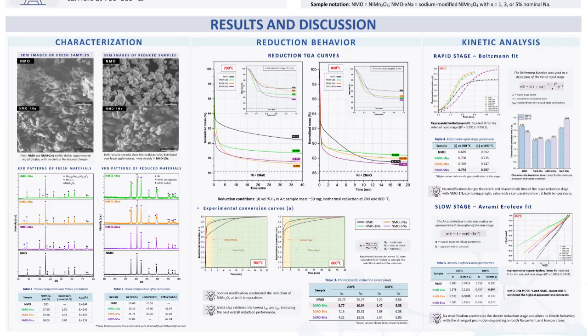The slower stage was analyzed using the Avrami-Erofeev model, where K represents an apparent kinetic rate constant. Sodium increased this rate constant compared with pristine NMO, although the strongest effect depended on temperature. The 3% sodium sample showed the highest K at 700 degrees Celsius, while the 1% sample showed the highest value at 800 degrees Celsius. Overall, sodium influenced both reduction stages, but its kinetic effect was not proportional to sodium loading.